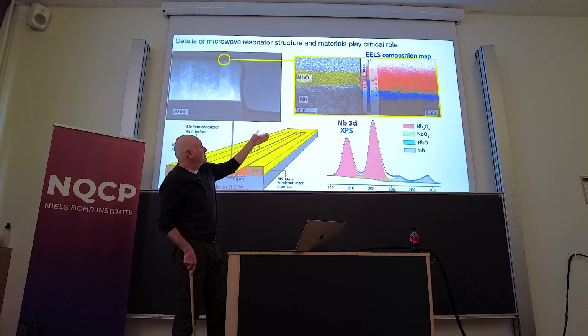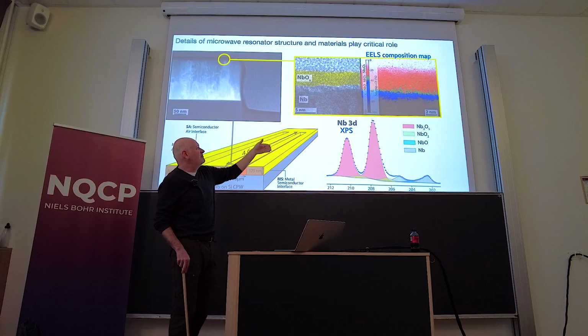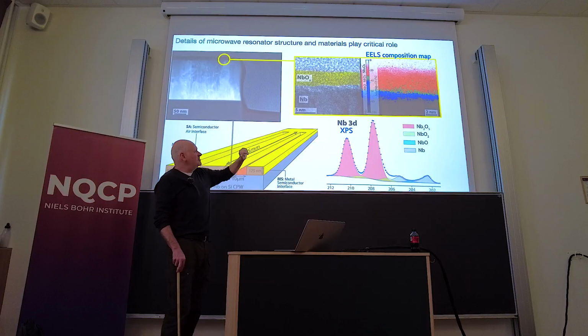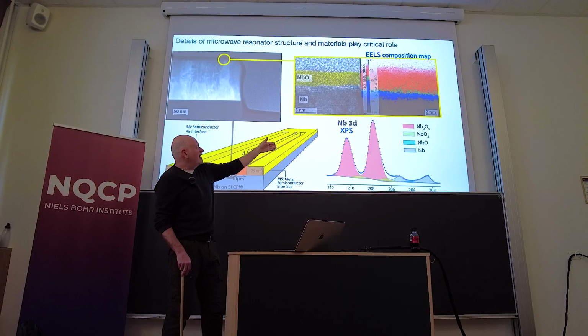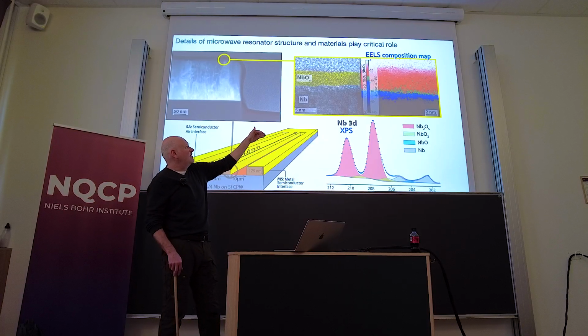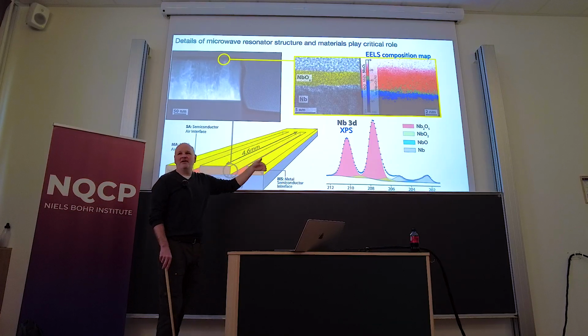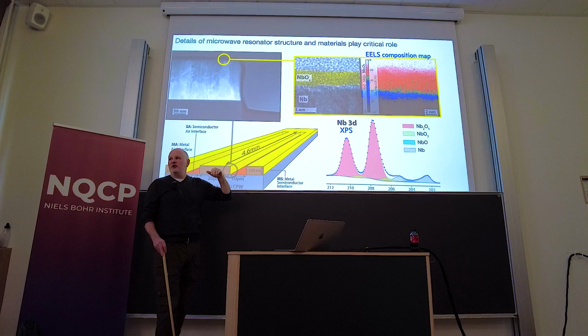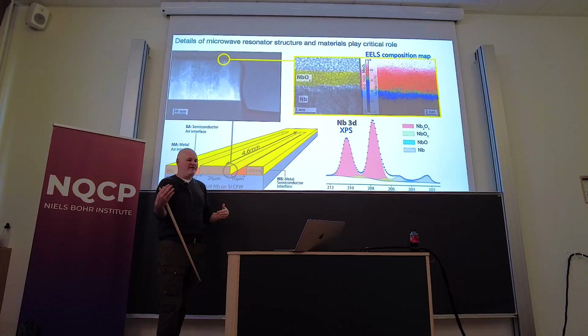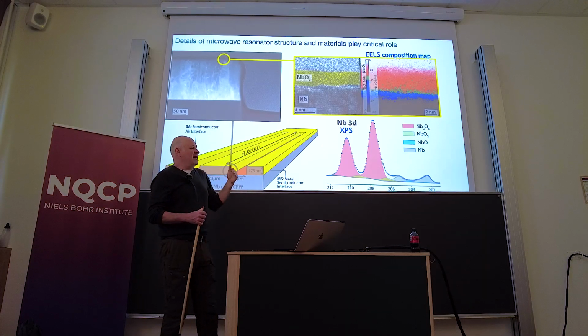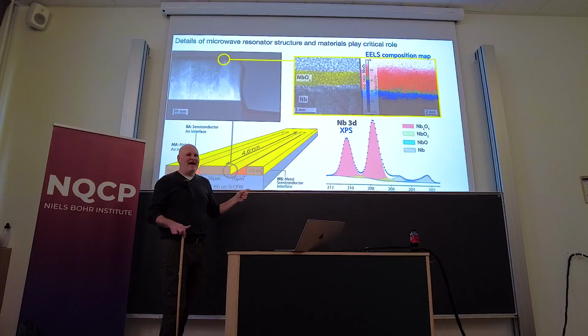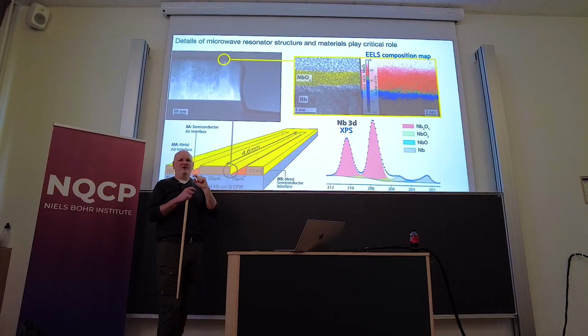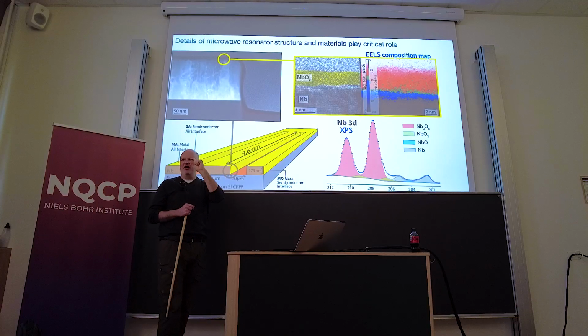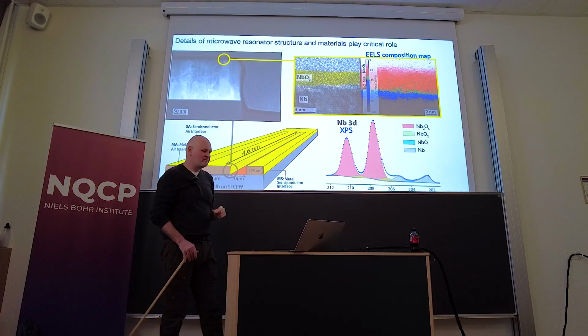And the different colors here are different ratios of niobium to oxygen. And as you go from the bottom, which is pure niobium, to the top, which is pure Nb2O5, you can see there's this gradient of concentration where you go from pure one to pure the other. And this is, again, very much outside of what you would expect from this PowerPoint slab diagram of niobium oxide sitting on top of niobium.